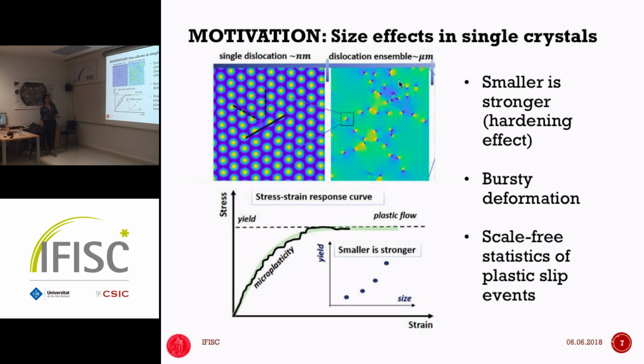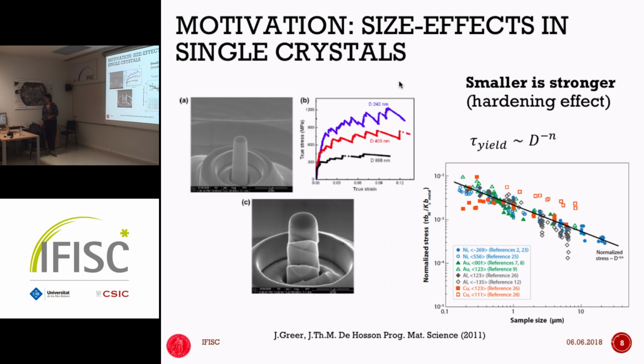And the second interesting effect that emerges when you go to small crystals, on the order of microscale and below, is this effect of smaller gets stronger. That is the yield point, this transition from strain rate independent to strain rate dependent. So here is time independent deformation, here is time dependent, like a viscous flow. So this transition is called the yield point, and this transition stress, I plotted this the other way around. Yes, it should increase with decreasing system size. Smaller gets stronger. Okay, I'll show you the experimental data where it's correct.